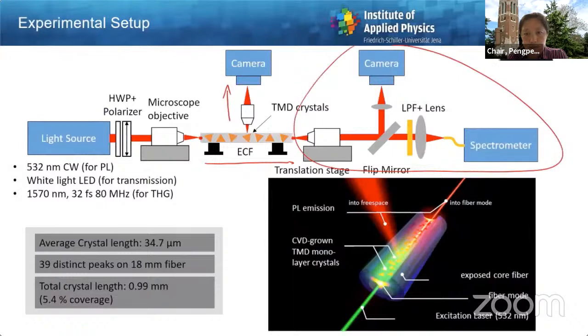We basically found that we have roughly 5% area coverage, and the total amount of crystals on an 18 millimeter long fiber of roughly 1 millimeter. And now keep in mind, usually you have to do transmission experiments with transition metal dichalcogenides, so you have an interaction length of 1 nanometer, and now we have an interaction length of 1 millimeter, which is like a 6 orders of magnitude increase. Okay.